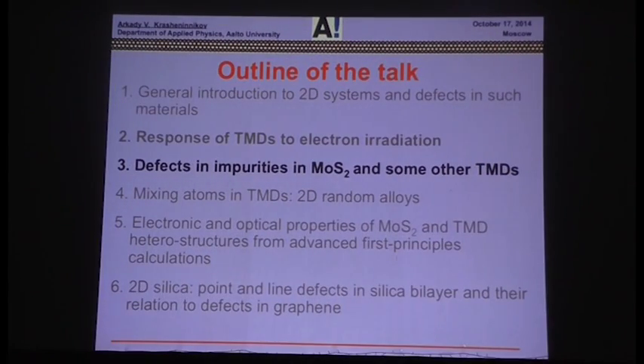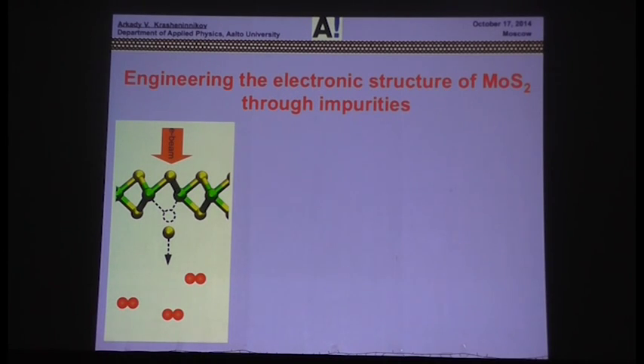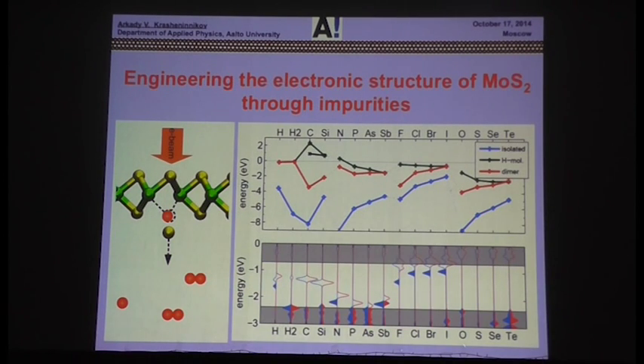Okay, so a little bit more about impurities and defects in moly disulfide. Basically impurities. As Dmitry touched upon, you may deliberately put something into your chamber, you create a vacancy, then the bonds will be passivated by some species which are in the chamber, because the bonds are really reactive, and this way you can dope moly disulfide with post-synthesis electron beam mediated doping. Depending on what you put in there, you may get donor or acceptor states, so lots of freedom here. But again, experimentalists, as Dmitry mentioned already, specifically TEM people, when you approach them with the suggestion to do that, they start hating you, because nobody wants to spoil the vacuum level in the TEM chamber, especially in high resolution microscopy.